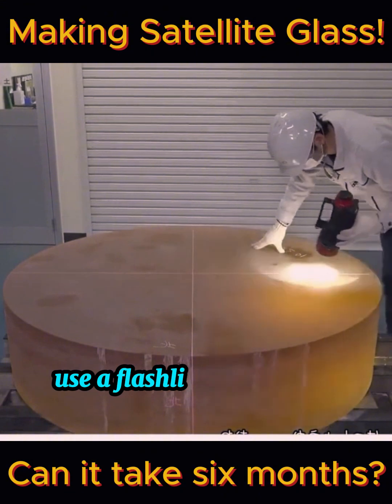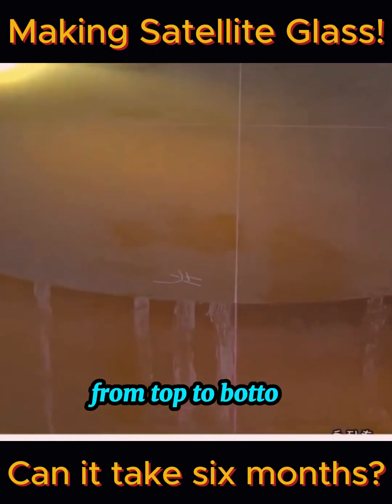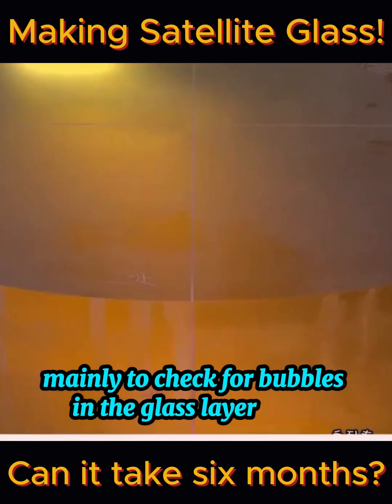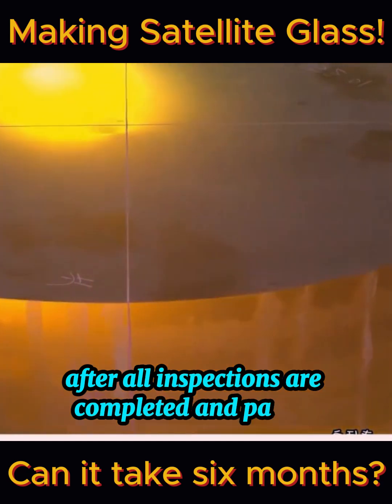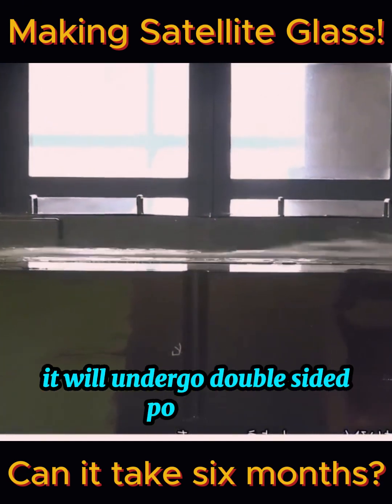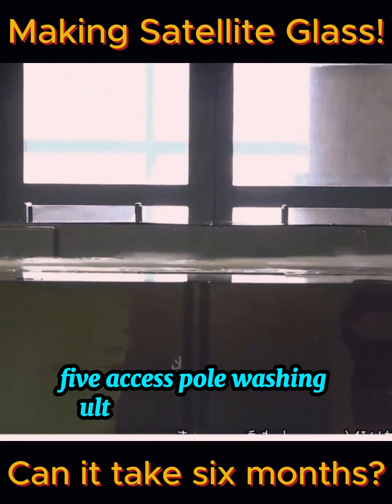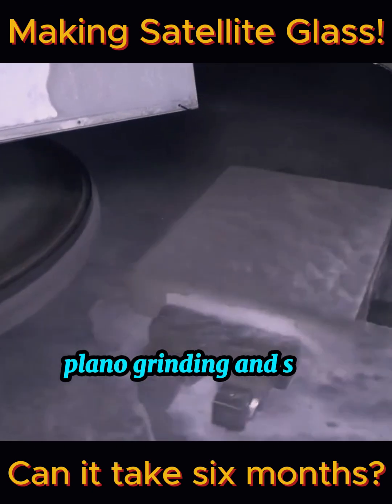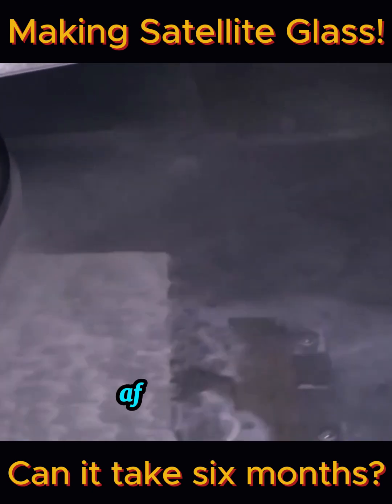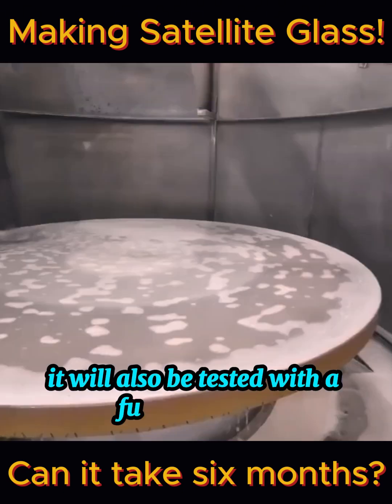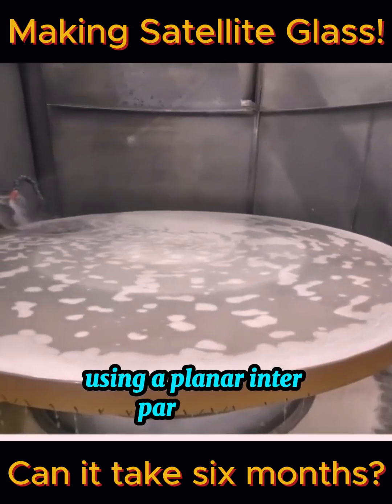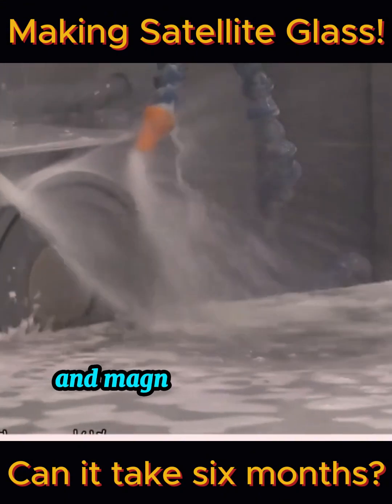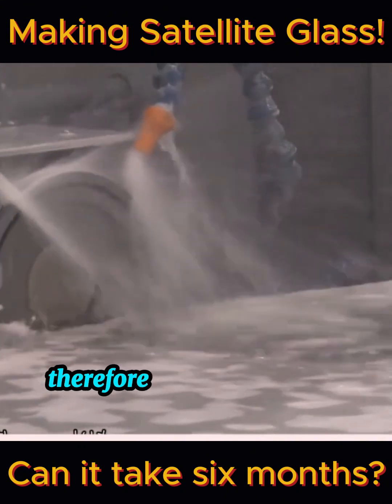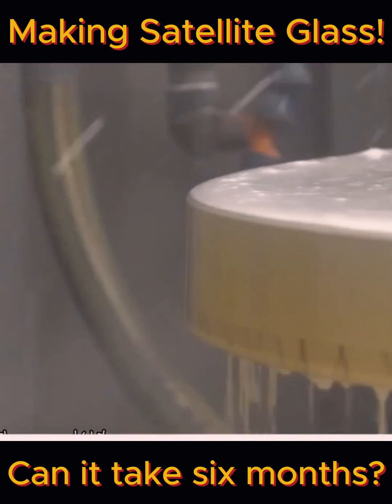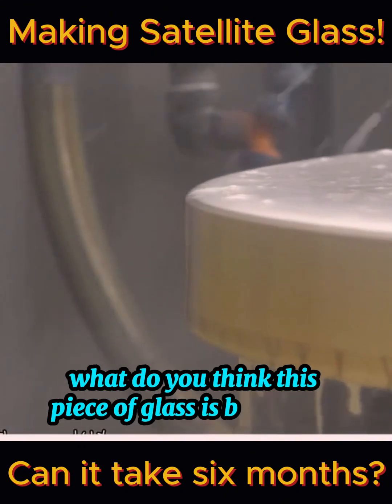Workers need to use a flashlight to inspect each position from top to bottom, mainly to check for bubbles in the glass layers. Only after all inspections are completed and passed, it will undergo double-sided polishing, 5-axis ball washing, ultrasonic processing, planar grinding, and slot cleaning, among other processes. After grinding, it will also be tested with a full set of data using a planar interferometer, 2-dimensional detector, and magnetorheological methods. Therefore, it will take half a year to be fully formed. So, what do you think this piece of glass is best suited for?